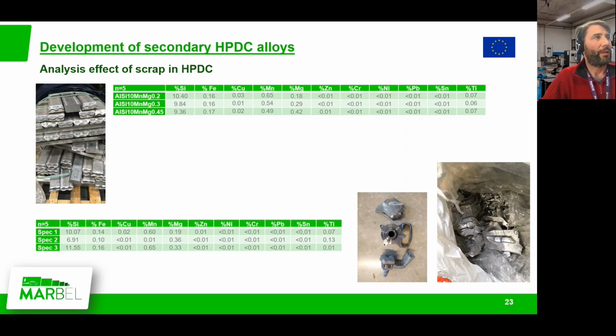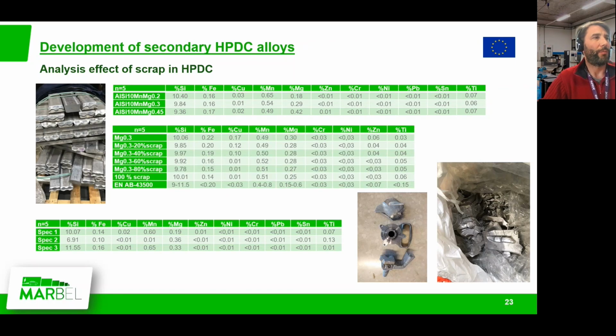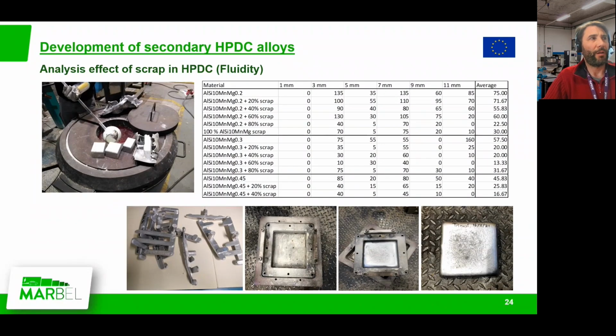For high pressure die casting, we have been working in MARBEL in a European project on the most typical aluminum silicon high pressure die casting alloy for structural applications. It's aluminum silicon 10 manganese magnesium. We have mixed it with a different amount of scrap and analyzed the effect the scrap content has on alloy properties.